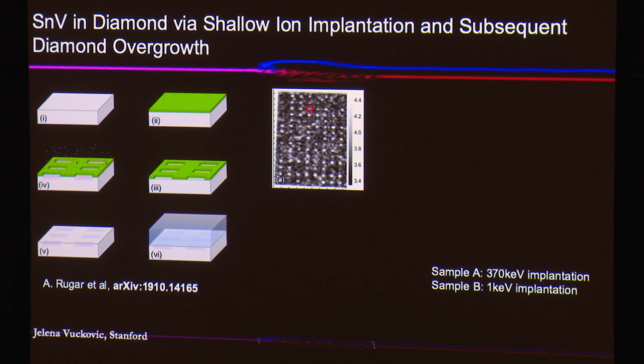Can you actually have them at every desired position? And can you make sure that fluctuations in their properties, inhomogeneous broadening, are minimized after you incorporate them in the lattice? When you just take a block of diamond and bombard it with ions, that generally is not the result, because you bombard it with very high energy ions, and tin is a heavy ion also, and you damage the lattice. Any damage in the lattice introduces strain, and your energy levels broaden, so your inhomogeneous broadening increases. So we've been working with the group of Nick Melosh, who is a material scientist at Stanford, on trying to minimize the damage, but still incorporate these color centers at the right positions.